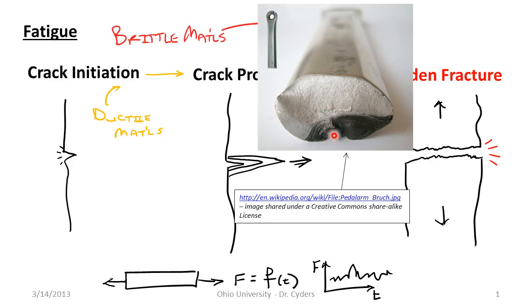Here is an example of a part that had some slow crack growth — this dark area here. This is a pedal crank arm from a bicycle, where this was pedaled and loads were exerted on it, and this crack grew slowly over time. It was tiny and internal, and eventually there was a failure initiated up here at this point, and you can see the waves. This fails like a brittle fracture, a sudden brittle fracture where you have a stress wave blowing through the material. It reached a critical point where this dark material was no longer supporting any load, so it became overloaded and the whole part broke suddenly.